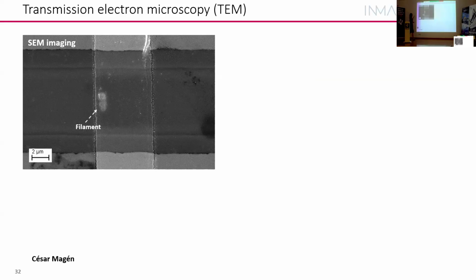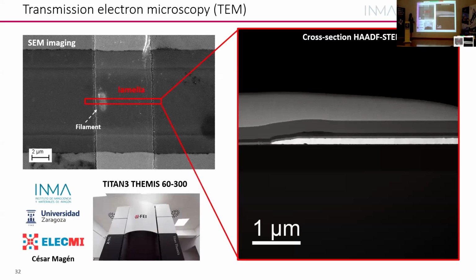Now we took one of these cross points, and we made a FIB lamella here. This was done in collaboration with César Magén also. And we can see in the lamella, as it was very long, this is the filament region, and here is a pristine region, and we can observe both in the same experiment.